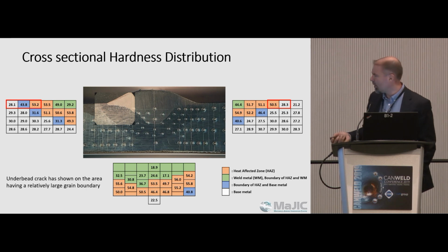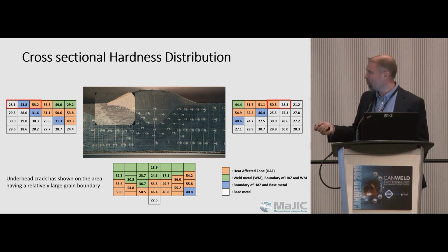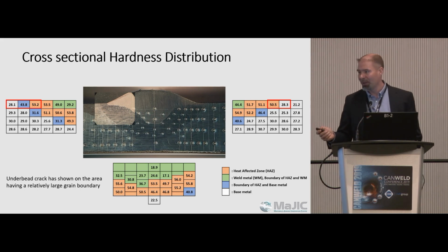And then I don't think you can see it, but from about here to here, we have a beautiful underbead crack that nearly popped that weld metal right out of the plate. So it is not recommended to weld 4340 without preheat, just for those of you that don't know that.